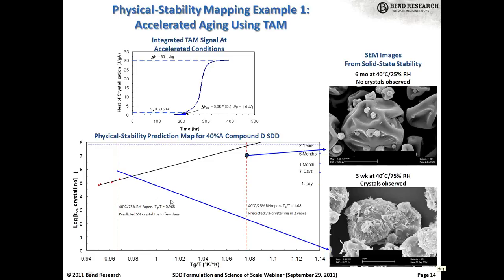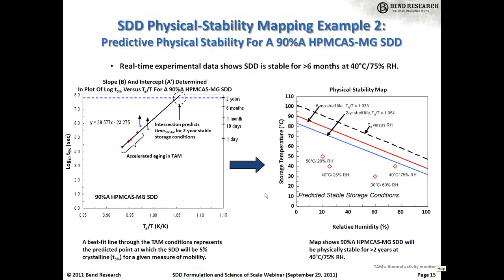So in this particular example, the prediction would be at 75% humidity and 40 degrees C, that you're going to see crystallization, again in that you have high mobility, but at 40 degrees, 25% humidity, that you will not see it for at least 2 years. And in fact, data shows that where stability is predicted, it's observed. So using this kind of methodology, you can map out solid state stability a little bit better.